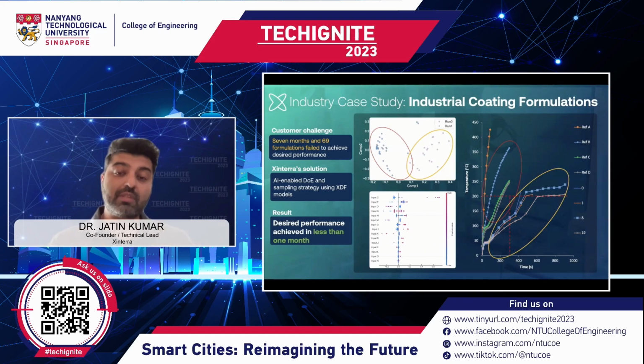Of course, the subsequent steps were to extrapolate then to 4 hours, which we did in 1 or 2 more cycles. And at the end of it, what the customer had was about 3 or 4 formulations that he can now commercialize and sell. And this was done in a fraction of the time that it would have taken him. If you think about 7 months and 69 formulations all in this space, you can probably extrapolate the time that it would have taken him to get there, and the opportunity cost that he would have lost. So this is the first major step forward towards a customer realizing success through our platform.